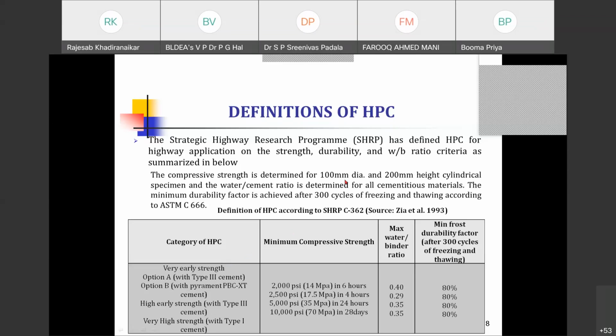And the water cement ratio is determined for all cementitious materials. And durability factors are in terms of 300 cycles of freezing and thawing. So there was a thrust on strength as well as the water binder ratio, because you know that the performance characteristics, particularly the porosity, that is the diffusion or permeation characteristics, depend on your water binder ratio. So they consider the strength requirement and also the water binder ratio and durability characteristics, that is 300 cycles of freezing and thawing.